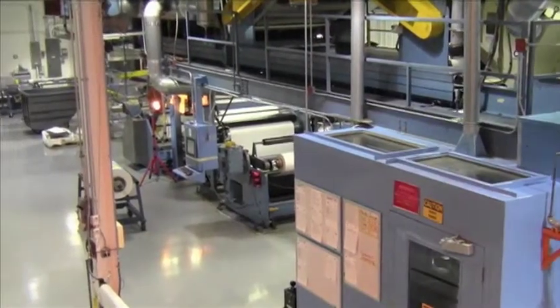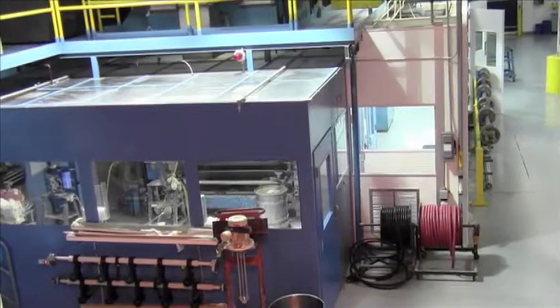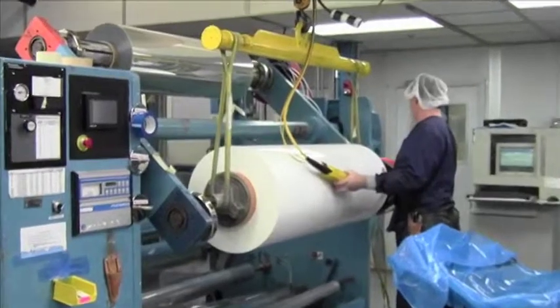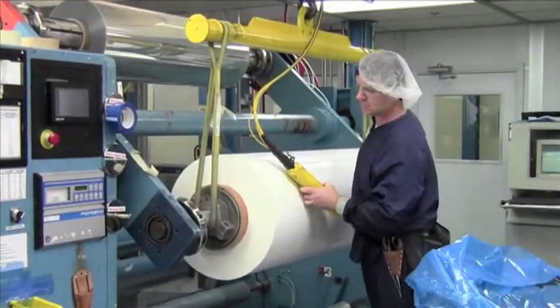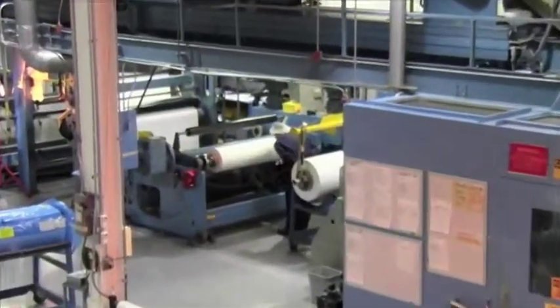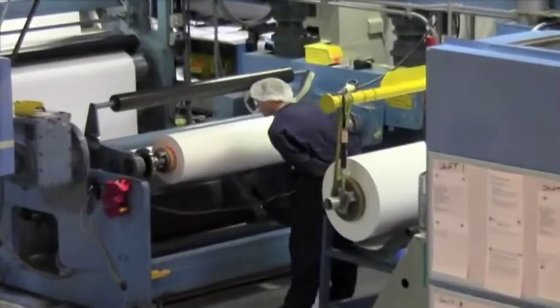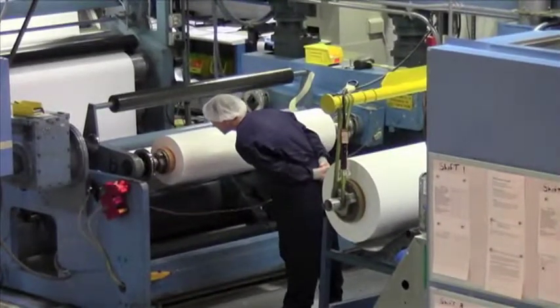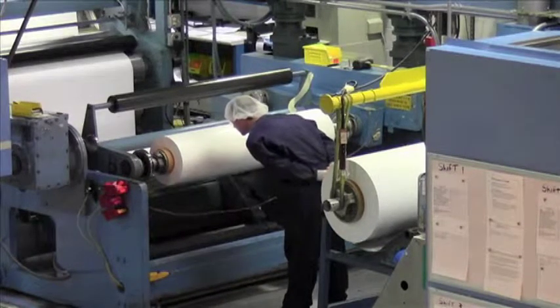All of our coaters are in a contamination-controlled environment, with 1 roll coater in a Class 10,000 clean room. We can accommodate rolls up to 40 inches in diameter and as wide as 63 inches, with the ability to coat up to 61 to 62 inches wide. Film thicknesses can vary from as thin as half a mil up to 30 mils thick. We have variable process speeds from 200 feet per minute down to 30 feet per minute based on the requirements or functionality of the coating type.